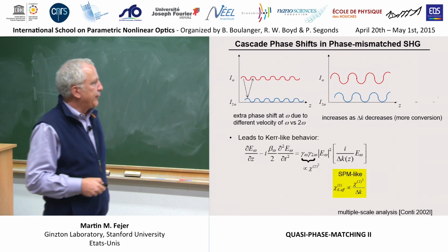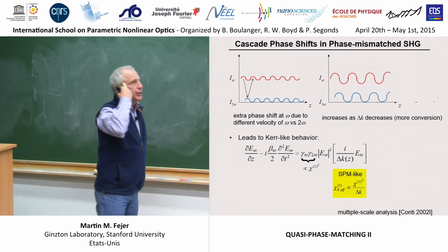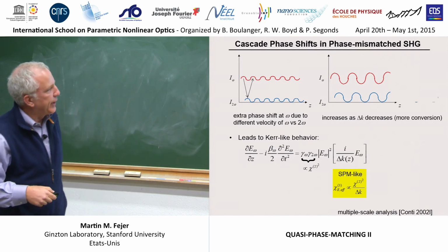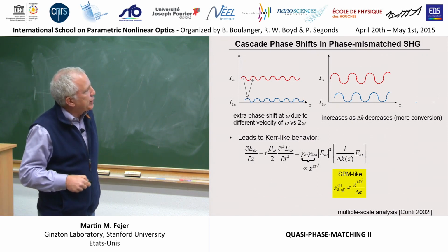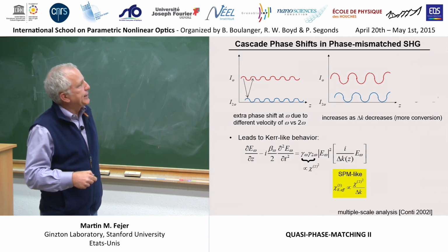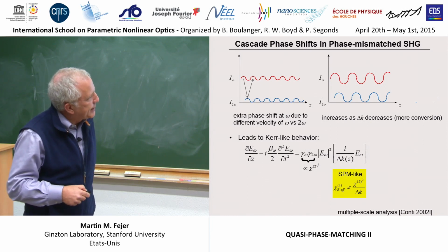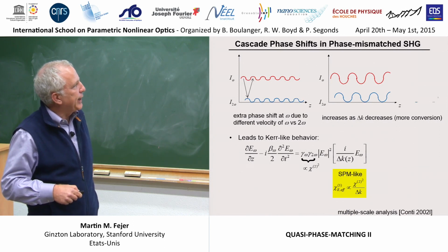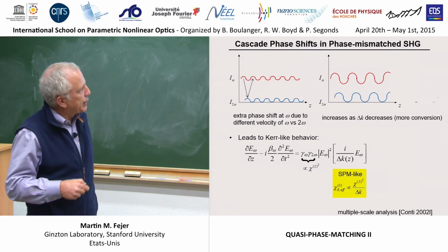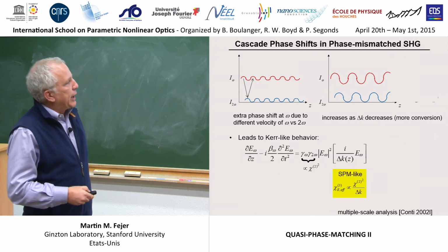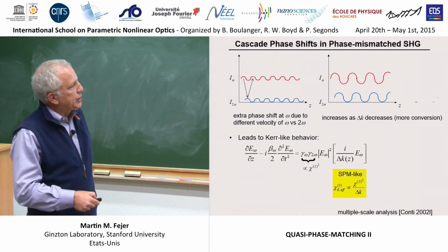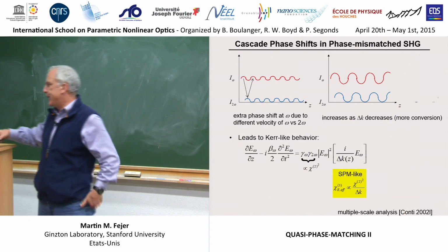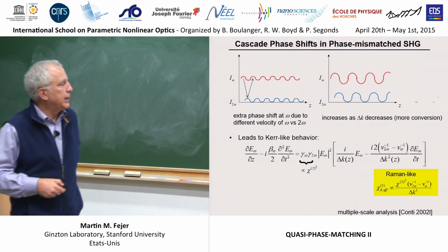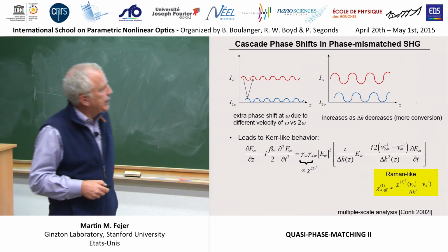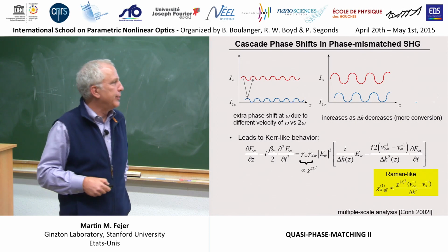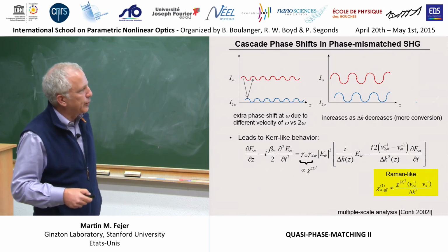If you do this more carefully, performing a proper multiple scale analysis of the coupled wave equations for the harmonic generation process, which you can find in the reference, you find that the evolution equation for the electric field at the fundamental contains the usual dispersion term, plus a piece that goes like chi squared over delta k. So the more nonlinear conversion you get, and the smaller delta k, you will have an effective chi3 which scales like the square of chi2 divided by the phase mismatch delta k. If you take the next order of this multiple scale analysis, you get a term reminiscent of a Raman-like term, except it goes like chi2 squared over delta k squared, with a group velocity mismatch thrown in.